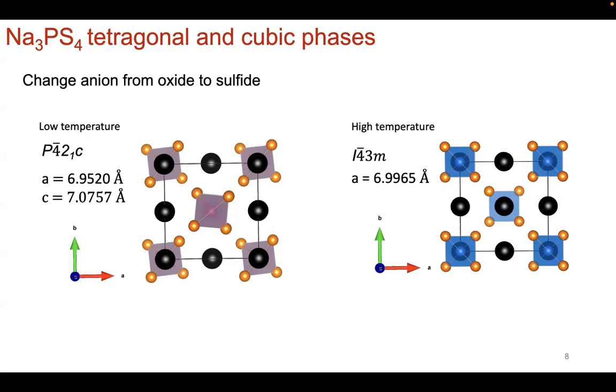The focus on Na3PS4 has also been because we understand a lot about Li3PS4. In going from sodium phosphate to sodium thiophosphate, you have the same advantages that you would have in lithium-ion solid electrolytes. So the sintering temperature is decreased, right? With what we've seen with the garnet system, you have to sinter at very high temperature, like 1,000 C, maybe 1,200 C, at higher pressures. Whereas with these sulfide-based compounds, you can do the sintering at lower temperatures and with less pressure, and sometimes maybe even cold sintering, while you apply the pressure. So there are advantages there.